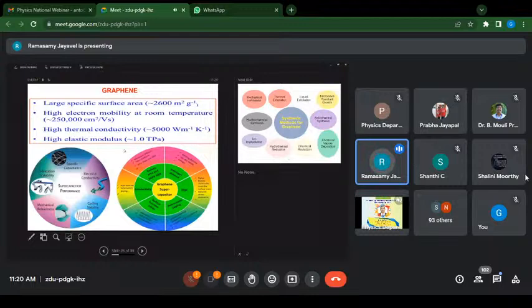Why has graphene become superior? Because the reason is it has got a very large surface area of 2,600 meter square per gram, and has a very high electron mobility at room temperature. The thermal conductivity is also very high, and because of the flexibility, it has got a very high elastic modulus. Okay, so when we use this graphene for supercapacitor performance, the process optimization includes achieving the higher specific capacitance with the improved conductivity, having a very high cyclic stability, so that repeated charge discharge will not deteriorate the material's performance, and mechanical robustness when we make large scale, and then fabrication scalability.